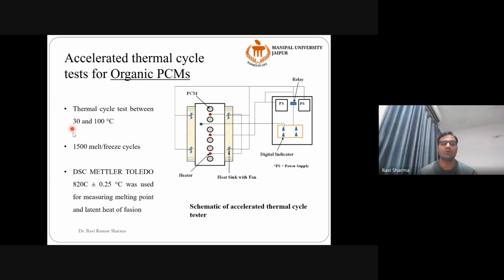The temperature was between 30 to 100 degrees centigrade. As I was mentioning, it will go from 30 to 100, 100 to 30 on its own, without any human intervention. So we did it for 1500 melting and freezing cycles non-stop.